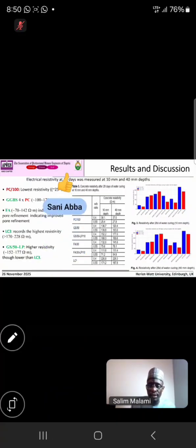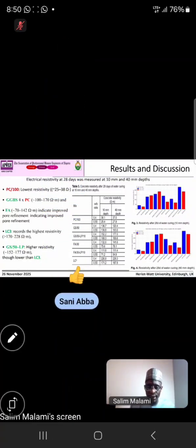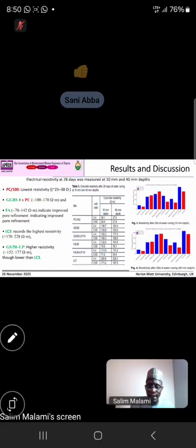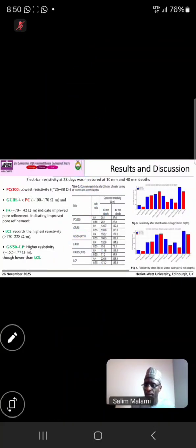So this is the result for the electrical resistivity. This is for PC. This is for GGBS. If you can see from the table, LC3 has the highest, even from the chart. This is for the one at 10 millimeter depth. This is for 40 millimeter depth. In both, LC3 has the highest, and PC, normal Portland cement, had the lowest in both charts.